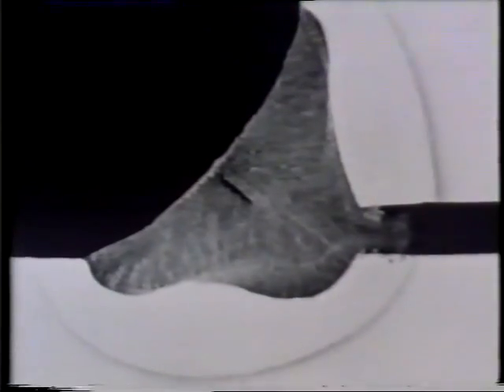Remember, fractures are much more likely to happen if there's something to initiate them. Have another look at the places where the cracks started. Yes, they started where there was a stress raiser, but coincident with the stress raiser, there was nearly always a weld. A weld effectively contains metal that has been cast and is therefore likely to have a lower toughness than the surrounding steel. But more importantly, a poorly made weld may already contain dangerous crack-like defects. It was these small cracks, depending on their orientation, that were the start of fractures that then continued right through the hull of the ship.